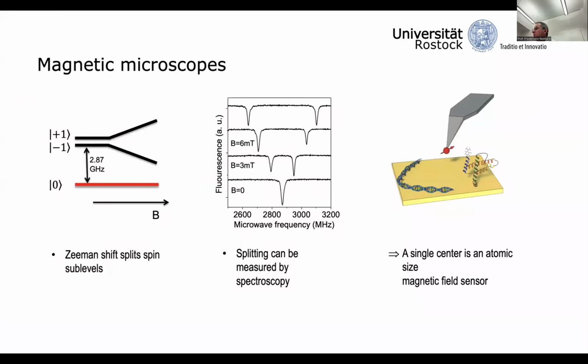Second important property: we can operate this defect as a qubit, and we can operate it as a magnetic field sensor. This is a very long story, which, due to the limited time, I will cut short. The electronic ground state of the nitrogen vacancy defect is a spin 1 triplet state. It's a stable electron spin with multiple sublevels. These sublevels differ in brightness, so we can optically read out the state of this electron spin qubit. Also, we can optically initialize it with a laser, and we can use it as a sensor because a magnetic